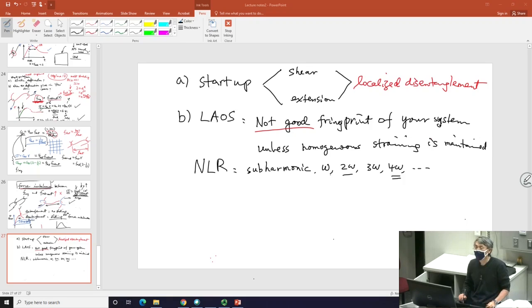If I recall, if there is edge fracture, that will give you even omegas. And if there is no edge fracture, you only have odd omegas, or something like that. Don't quote me, but we had papers, I understood that issue before. It certainly means you can look into that. People could claim this to give you a rheological fingerprint only if you have homogeneous shear. Then we had movies showing it's not. You can have shear banding. Okay?